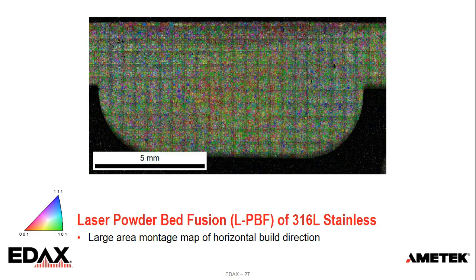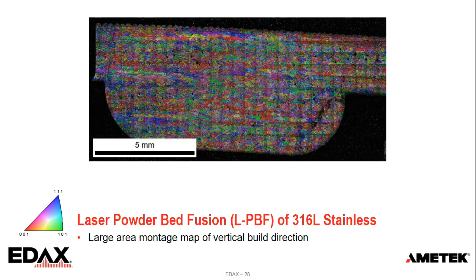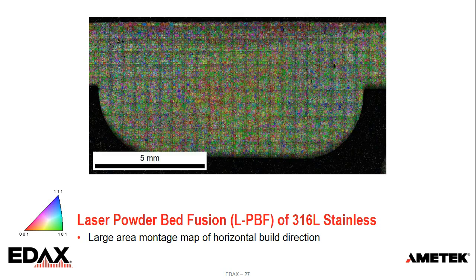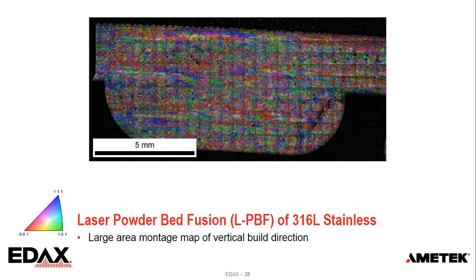Whereas if I compare that to what's termed the vertical build direction, this is where the build plane passed left to right, not out of the plane of the surface for this particular sample. If we look at those, you can see the shape of these two samples is essentially the same, but they were built in two different directions. That's important because if you were to look at a part and they look the same, you wouldn't realize that the mechanical properties are actually defined by the microstructure. And if the microstructure is different from one to the other relative to the shape of the part and the directionality of an applied load, you can get very different performance. That, I think, sparks some of the interest in understanding the microstructure of these 3D printed parts.